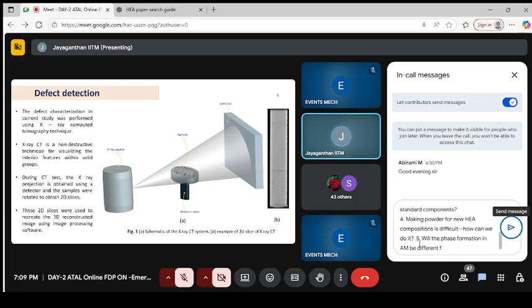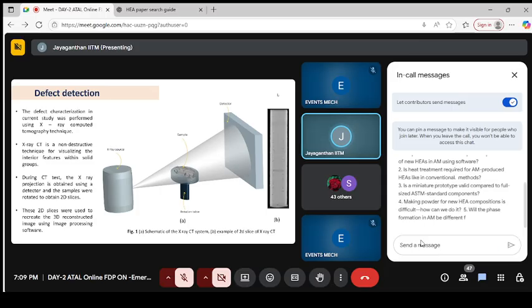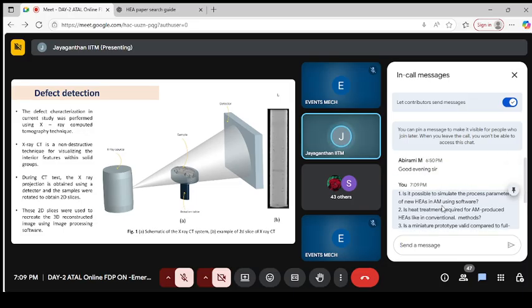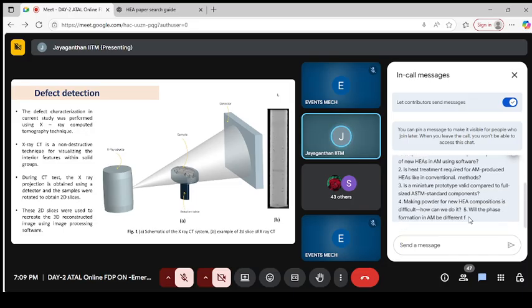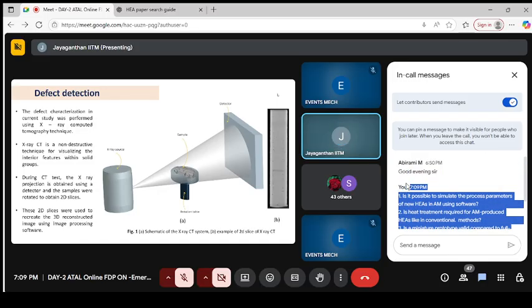So these are internal defects. Why do we use X-ray CT scan? Internal defects are not visible to the naked eye. It may be a micron size pore or even a millimeter size pore. A millimeter size pore you can see with the naked eye. If it is micron or submicron, I have to do X-ray CT scan to analyze internal defects.